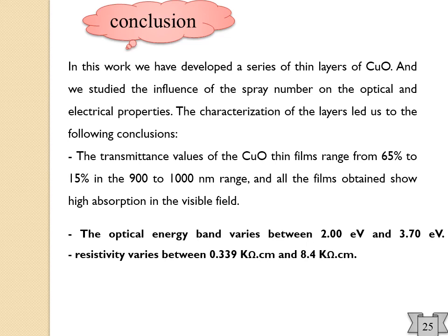The optical energy band varies between 2 electron volts and 3.70 electron volts. The resistivity varies between 0.339 kilo ohm centimeter and 8.4 kilo ohm centimeter.